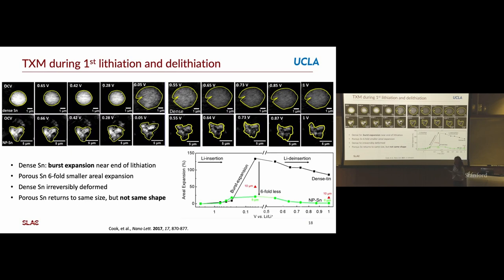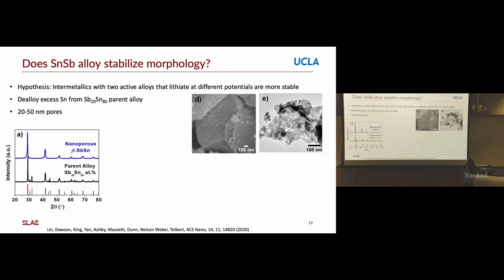When we looked at the cycling data, it seemed like things were going well, but I think we can improve this. And so that's what we did. We went back to our collaborators at UCLA and they said, well, we can try an alloy. Antimony also lithiates, but it lithiates at a different voltage than tin does. So if we create a tin antimony alloy, we'll have some of the atoms lithiating at one voltage, some of the atoms lithiating at a different voltage, and it'll be a more stable structure because you have this dual alloy, which is supporting your volume changes and supporting your structure as the other one alloys.